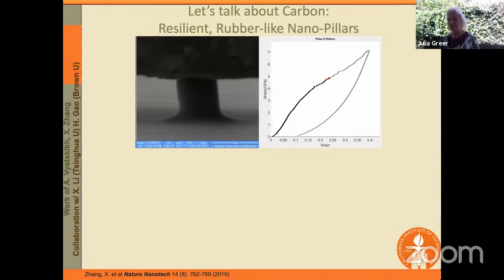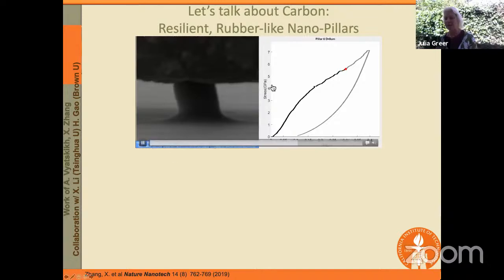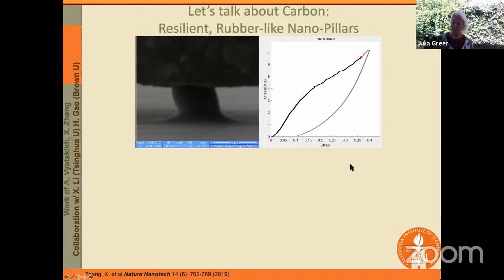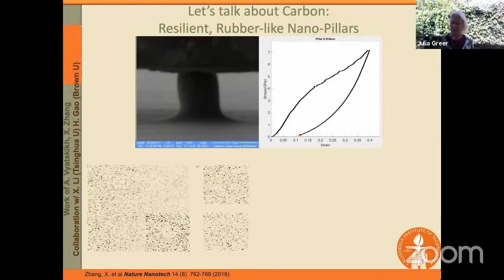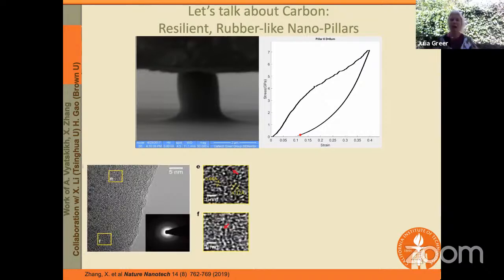And look what's happening with this pillar. It's now at a stress of 5 gigapascals. So this is a very, very high stress. You can see that as we're compressing it, it's really not enjoying itself. It's bending out of plane, of course, and then it fully recovers. So this very brittle, very strong carbon material thinks of itself as rubber. So how can that be? That is very, very unusual, right?